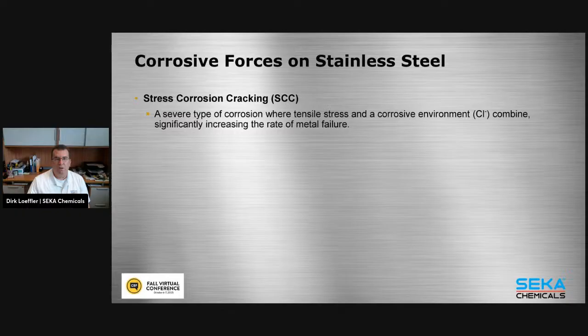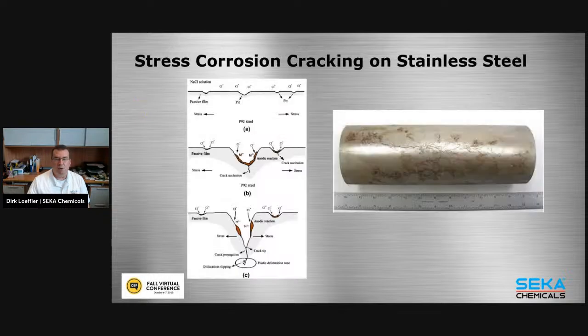Stress corrosion cracking, probably the most feared one of all. This generally will result in a destructive failure of the stainless steel, where the pitting and the tensile stress get so bad that it will literally eventually cause a failure of the equipment. On the left side here, we see the mechanism, how this will work, and this is actually an ongoing self-maintaining process that will just keep getting worse and worse as the pitting progresses. And this is a typical visible example. Sometimes in the beginning stages you can't even see it, but you see how all the cracking here is happening. Again, this will eventually lead to failure.